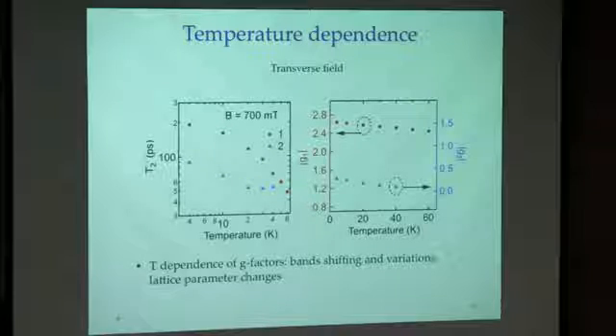And this G factor change with temperature is not too surprising if you consider that the band structure also changes with temperature. Bands shift, and the parameters of the band structure also change, because the lattice parameter of the material changes with temperature. As you increase the temperature, of course, the structure gets more symmetric.